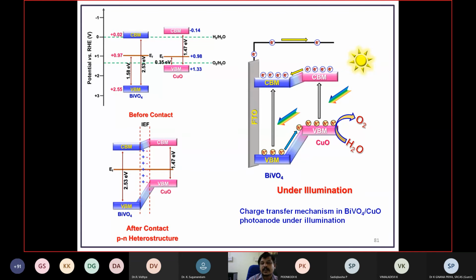So now our direction is moving towards making thin films for this photoelectrochemical water splitting, instead of developing the material by the sol-gel method, hydrothermal method or precipitation method. From our own experience, we suggest that if you want to do photoelectrochemical hydrogen production, better you fabricate the electrode directly by depositing the material over the surface of the substrate.